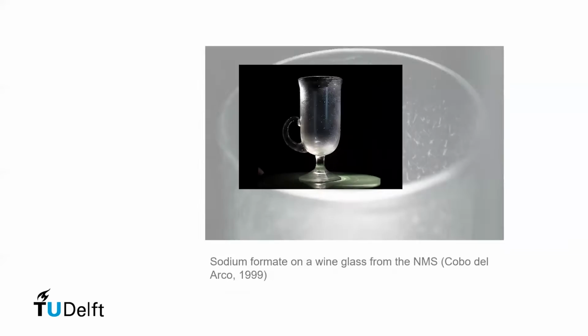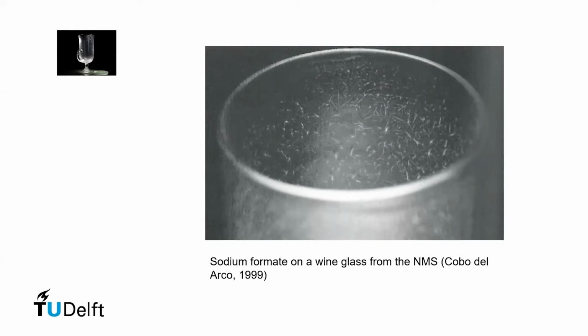Okay, next slide. Next click, yeah. And what this moisture actually is, is dissolved salts. What actually happened is that salts have formed on the surface and attracted moisture from the atmosphere. So that when glass dehydrates, these salts crystallize when the glass is kept in a dry environment. And you can actually see the crystals forming on the surface of the glass. So that's also a typical example of a sign of degradation, the formation of crystalline material on the surface. Okay, next slide, please.